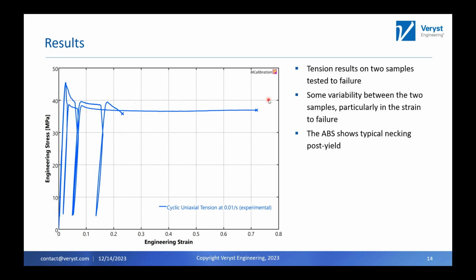The big difference is that one of these failed at, we'll say, 25% strain. The other one went to 70% strain. This is an N equals 2. I wouldn't put anything on this. Failure is a stochastic process, so making sure that you test multiple samples, if that's what you're interested in, would be important.